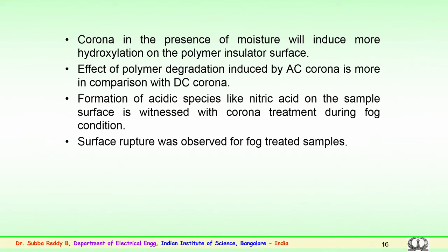The formation of acidic species, particularly nitric acid, on the sample surface was observed during the corona treatment, particularly under the fog condition, that is a normal mist condition. This could lead to surface rupture and degradation over a long period of time. This surface rupture was also observed for both types of fog-treated samples, that is the normal fog and also the acidic fog-treated samples. So, similar phenomena could occur in the field. Once this occurs, the hydrophobic properties of the material could be weakened, and the sample is likely to degrade faster in the field.